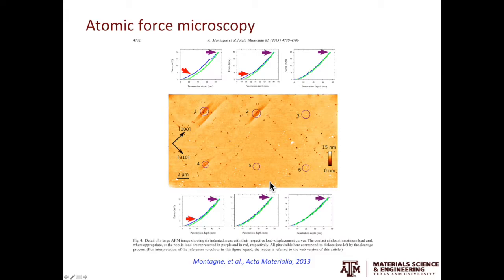In addition to optical microscopy, you can also use atomic force microscopy to reveal dislocations. The figure is taken from an ACTA paper published by Montagne and coauthors. The sample is magnesium oxide. Certain areas of the specimen have been indented using a nano-indentation device. Similar to the optical micrograph example in the previous slide, those dots you see, these are etch pits. And also you see those inclined lines, these are slip traces left behind by the nano-indentation.